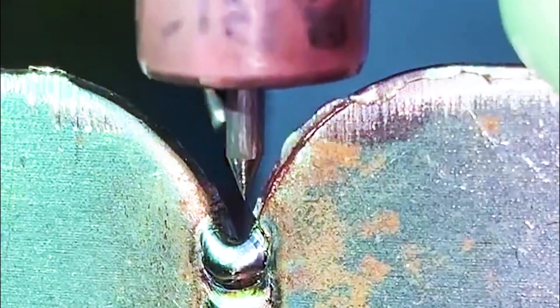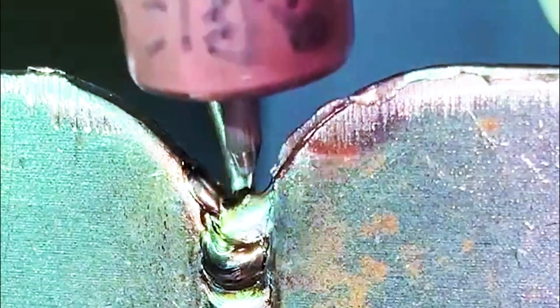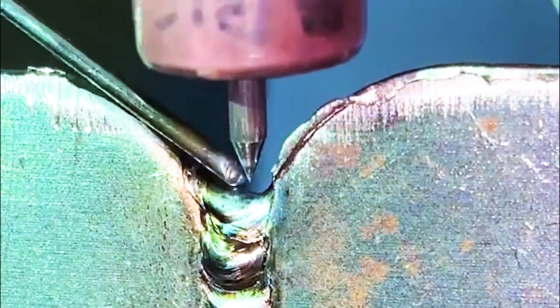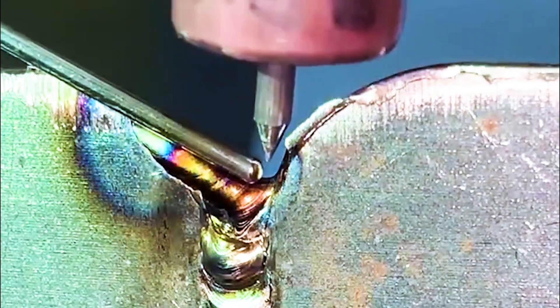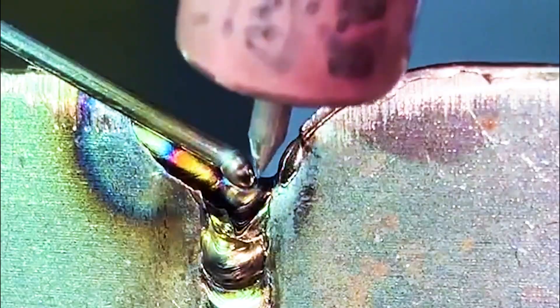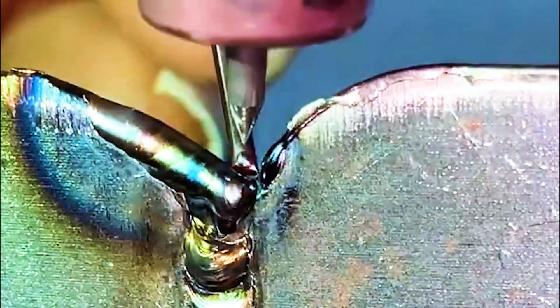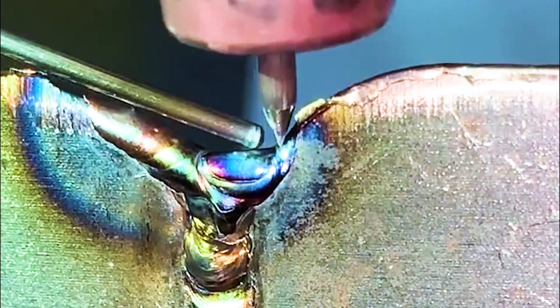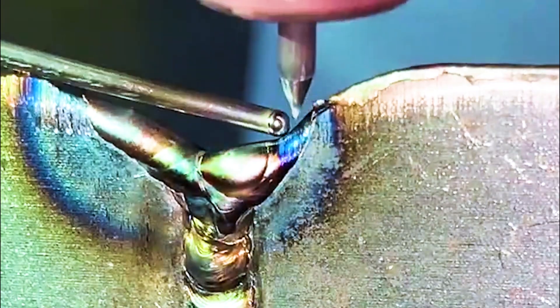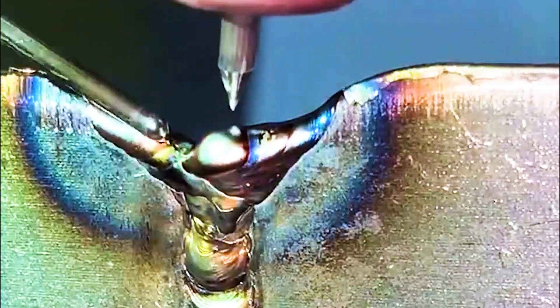Can the cold welder really be cold welded? The cold welding machine is not truly cold welding, but the temperature remaining on the workpiece after welding is low. When the temperature is too high, the stress of the plate will change — the heat affected zone will appear with discoloration and deformation. In fact, the temperature during the welding process is very high; the instantaneous temperature will exceed 2200 degrees.